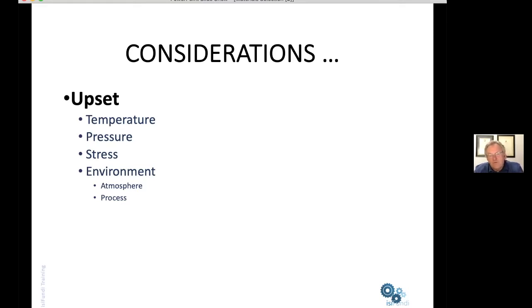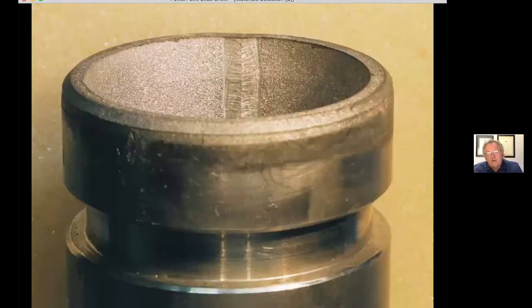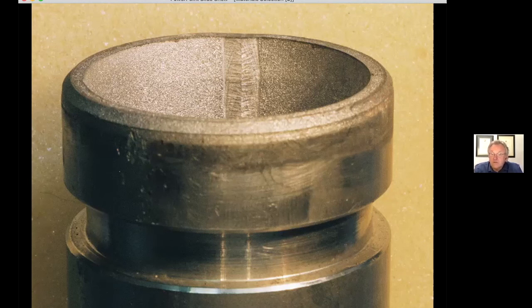Interestingly enough, one of the upset considerations that I've come across on a couple of instances is that of electrical interference in the process industry. Here is a piece of pipe from a very fancy, very expensive valve made out of Hastelloy C276. And as you can see, it has significant internal corrosion. This piece of plant was designed and developed to handle hot sugar solutions with very high hydrochloric acid content as well. On paper, everything looked fine, and yet this component failed.